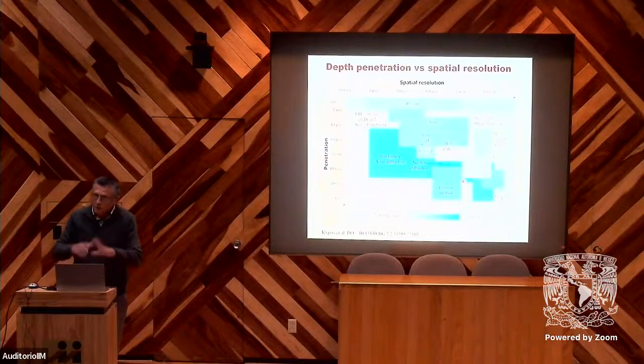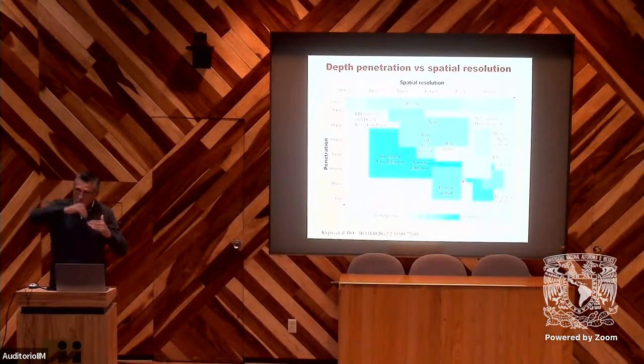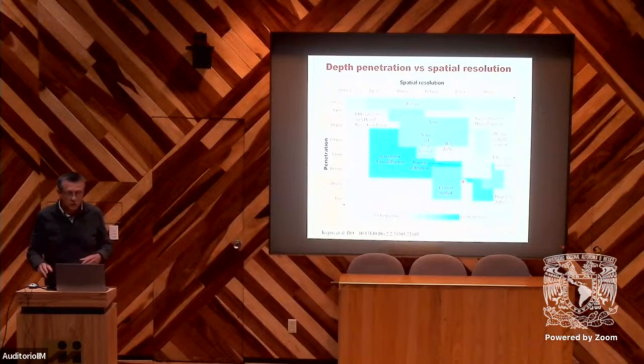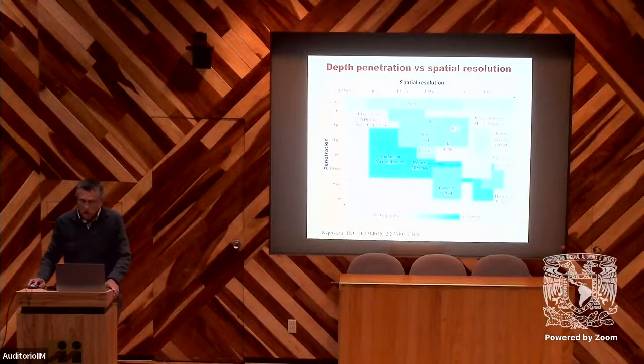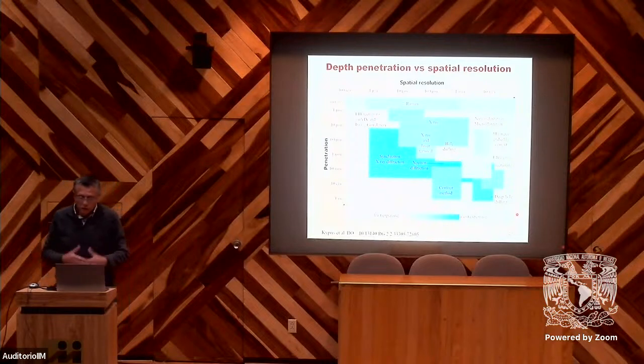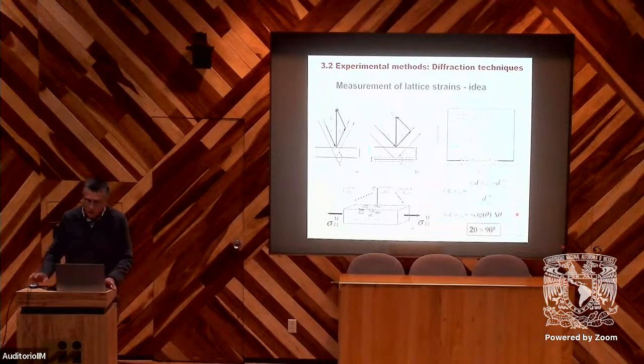So if we compare now all these methods in terms of penetration depth or in terms of spatial resolution, we can observe here that if we use the different X-ray methods, that means classical X-ray, synchrotron, and neutron diffraction, we cover a very large field in terms of penetration and spatial resolution. So that's why we developed these methods, and we use all these methods to analyze the residual stresses for different studies.